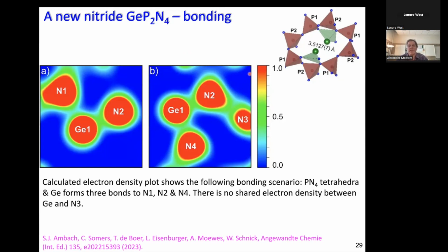And the first interesting thing was that when you look at the bonding scenario, these are from Cody and Tristan, some electron density plots, then it turns out that there are these PN4 tetrahedra that you see here, and germanium, there are 4 non-equivalent sites, and germanium only bonds and shares electron density with 3 of those.